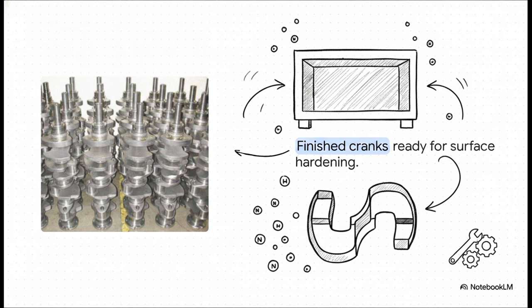After the initial shaping, these cranks go through a surface hardening process called nitriding. They get sealed in a special container and blasted with heated ammonia and nitrogen gases. The gas chemically reacts with the iron on the surface of the steel, essentially baking a super hard outer shell right into the metal. It's usually only about 2 to 20 thousandths of an inch deep, but that microscopic layer vastly increases the part's wear resistance and fatigue strength.